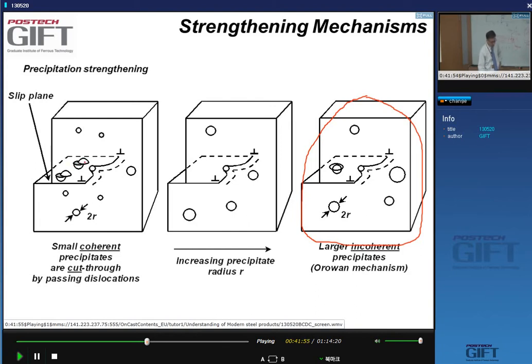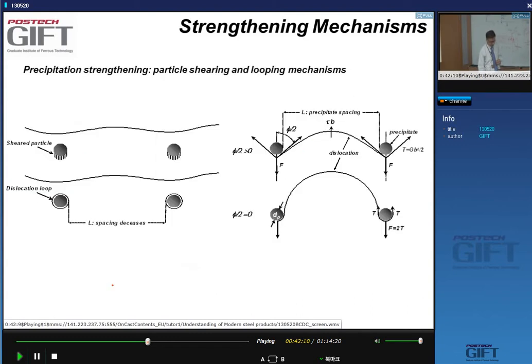This cutting of particles happens when you have coherent precipitates, because the dislocation has to pass through the particle, and usually you need very small particles also. The difference between the two is that after the passage of the dislocation, in the first case we have a sheared particle, in the other case we have a dislocation loop around the particle.